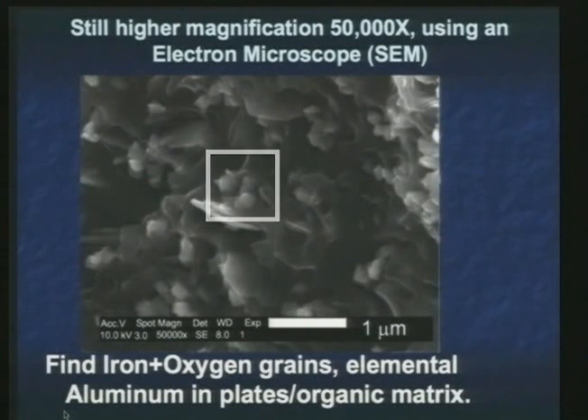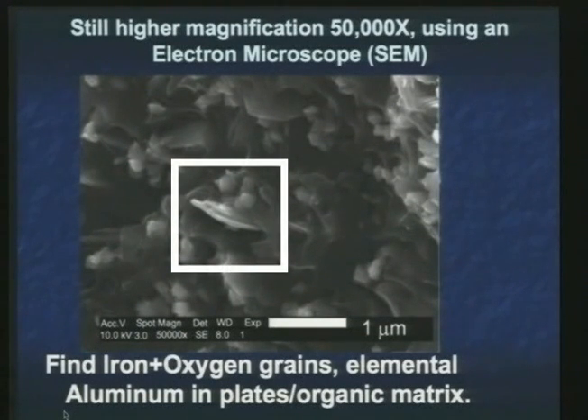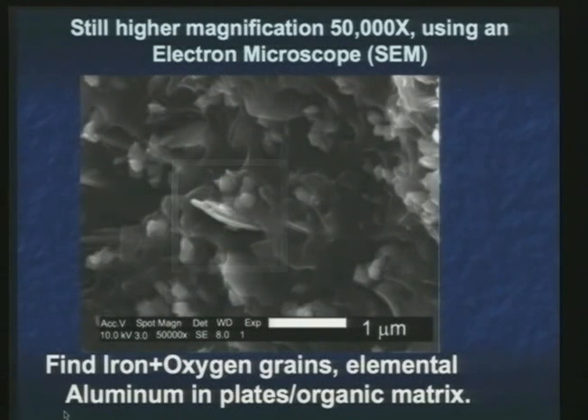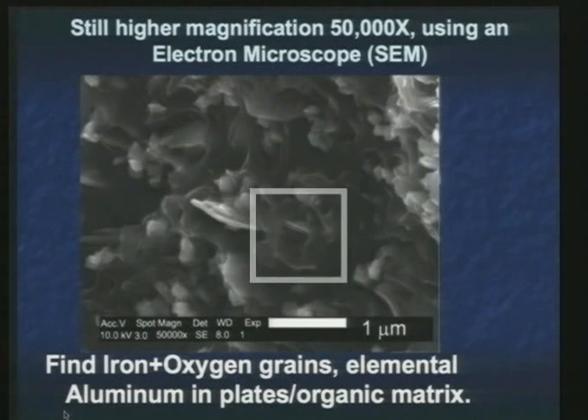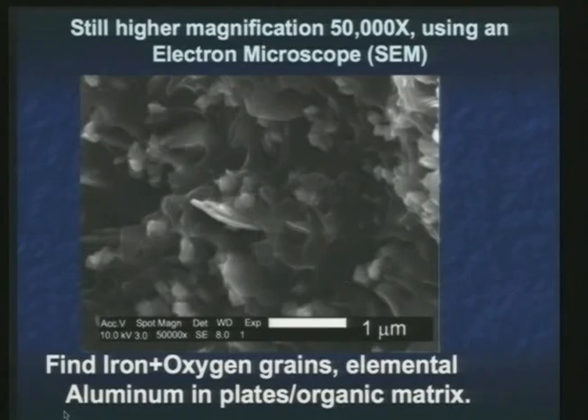SEM image as well. These are grains, and they happen to be rich in iron and oxygen. And the aluminum is found in these plates. Can you see right near the center below that set of grains, there's aluminum. And then around this, there's this kind of wavy material. This is an organic matrix rich in carbon.